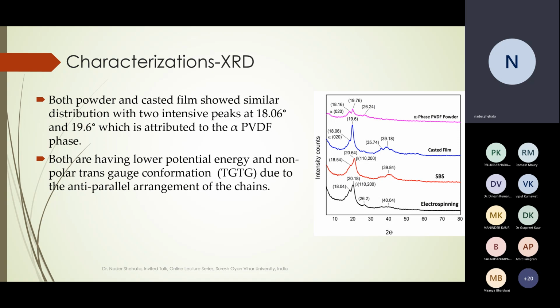For example, there are some angles like what's shown here. It's related to both powder and casted film. And these angles, or these peaks, are more related to the conformation of the alpha phase, which is called trans-gauche conformation. This conformation of the bonding is a matter of orientation of the atoms inside this organic solvent, but this structure is mostly non-polar. Okay, so in this case we will have an anti-parallel arrangement of the chains, and consequently we will have a very weak piezoelectric performance within these peaks.